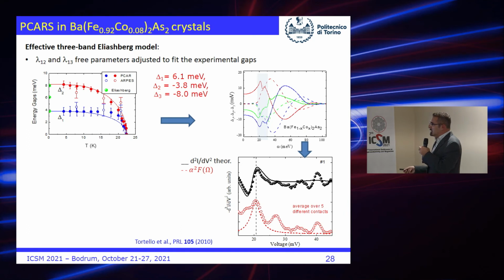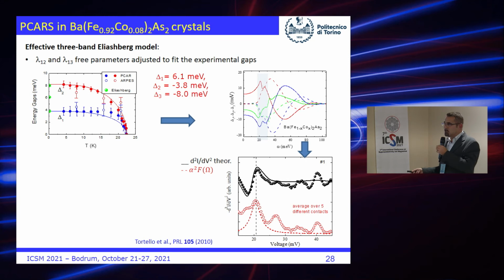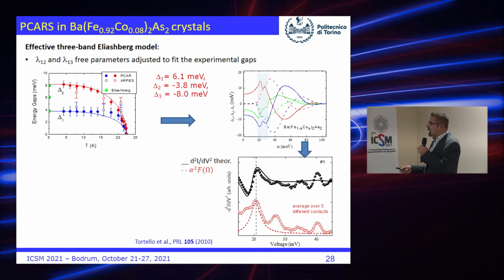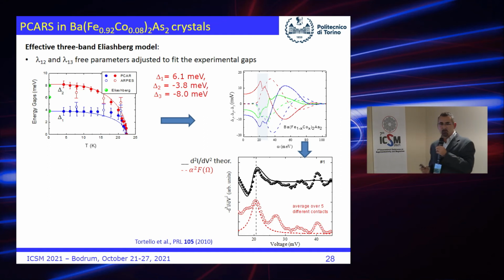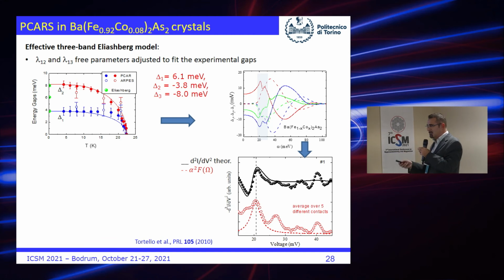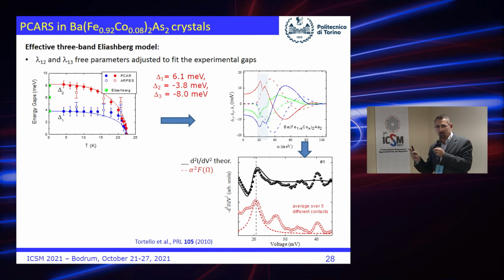Then let us calculate the gaps. The gaps are here, 1, 2, and 3. You see, but the one in the middle has nothing to do with your measurements. Yes, it is true, but it is surprisingly similar to that measured by ARPES. So it is possible that we see 2 gaps, ARPES sees 2 gaps, but they are not exactly the same. For sure we see both the small one, but the large ones that pertain to different electronic bands for some reason are not well resolved.